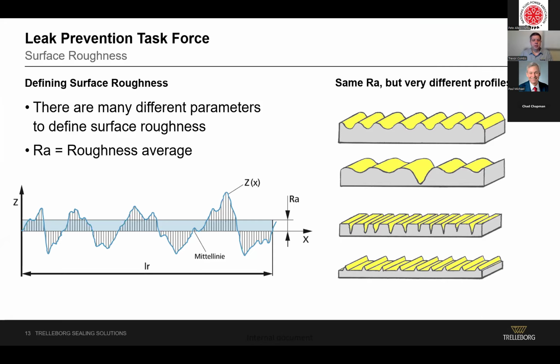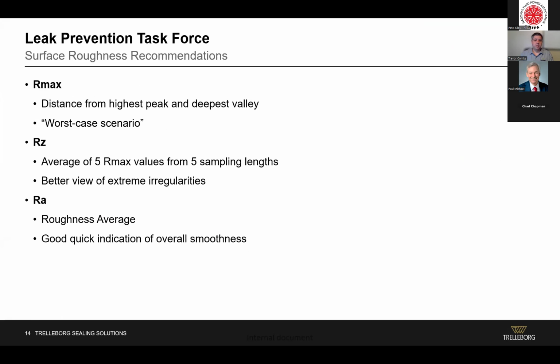And what you can see here is that you can have the same Ra, but very different profiles, especially as it relates to the seals. A seal is going to be affected dramatically by the different profiles there on the right, even though they all have the same Ra. So what that says to me is that Ra alone isn't enough to define the necessary surface finish for a rod. And so what we like to do is recommend a few other parameters. When you're looking at the surface roughness, you want to look at a few other parameters.